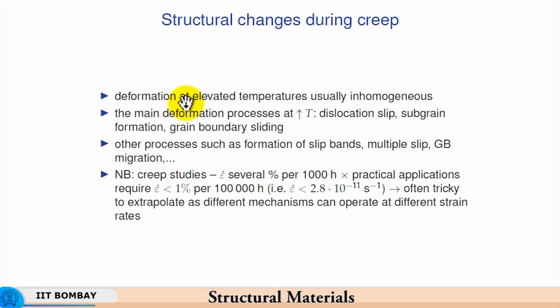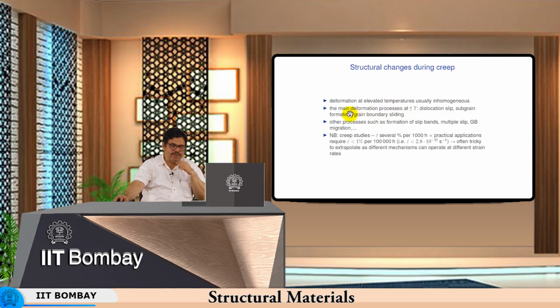The structural changes that take place during creep are diffusion related changes. There is a lot of diffusion taking place because of time, temperature, activation energy type of processes operating in the material. The deformation at elevated temperatures is usually inhomogeneous, and as the temperature increases, dislocation slip decreases. The component of dislocation slip will reduce, subgrain formation will take place, and recovery processes will start, and grain boundary sliding will become increasingly important as the temperature goes up, because as the temperature exceeds the equicohesive temperature, grain boundary sliding will dominate the entire set of mechanisms. That is why with increase in temperature, the three different mechanisms which are concurrently operating will change in terms of emphasis, or contribution.